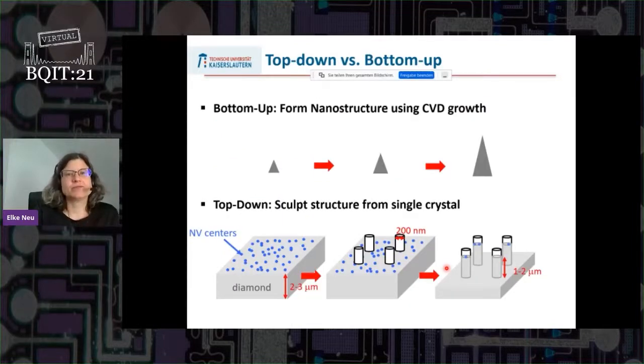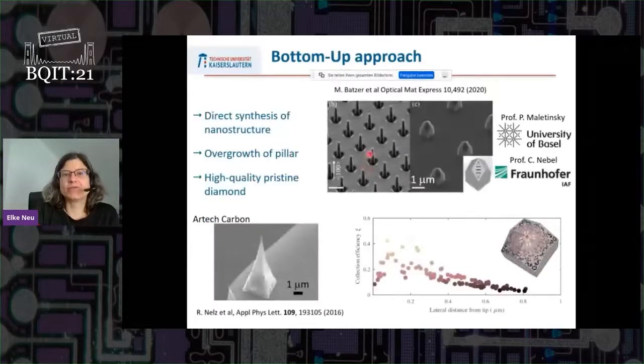And the two types of structures we are typically working with are pyramids, so this is really what you think of when you think of a tip, and cylindrical nanostructures that we call pillars. These pyramids are typically formed by growing. You use chemical vapor deposition to grow diamond, and this forms a pyramid that you can see here. So you take a pillar, you overgrow it to form a pyramid. If you do calculations, you see that for NV centers placed close to the apex of the tip, you get the best collection efficiency, so the most efficient sensor readout. This is very good. However, it's very hard to place the color centers here.